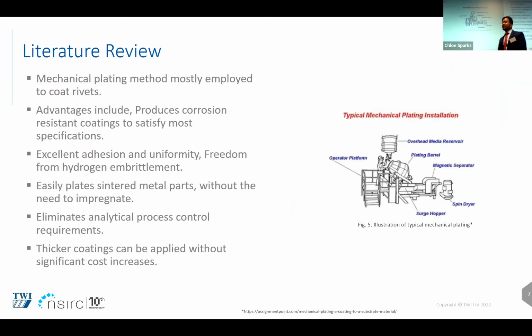So how are these coatings formed? They are widely produced in industry by using the mechanical plating method, where we put the rivets under an overhead feeder, and the rivets go into this barrel. It's rotating with a certain RPM, and our overhead feeder supplies the coating material that is poured into the barrel. It can be automated as well as manual. An automatic feed system can be used here that will feed the rivets in.